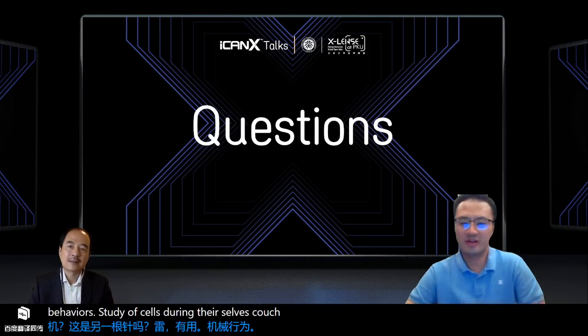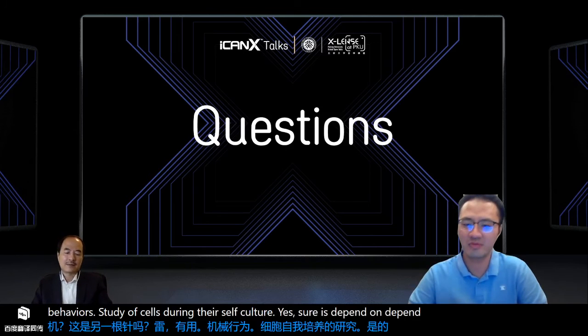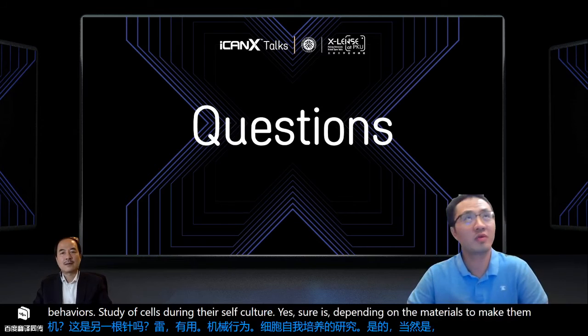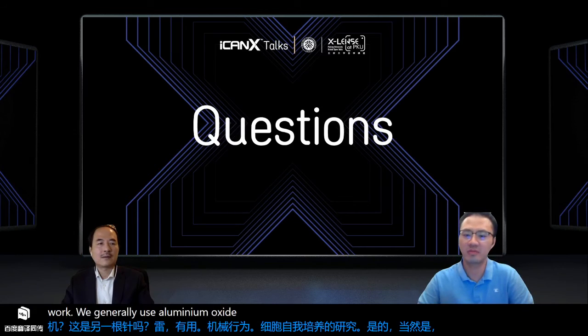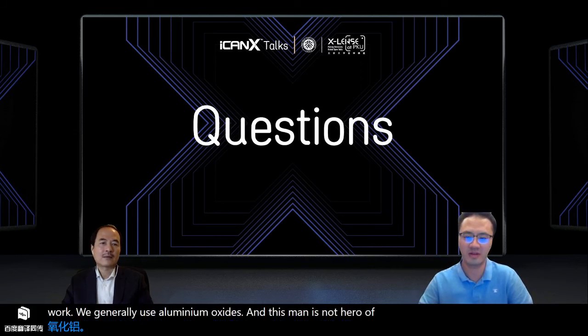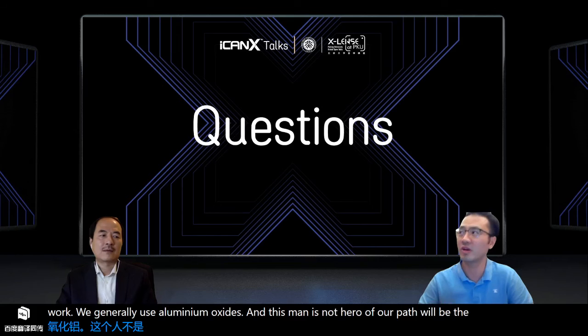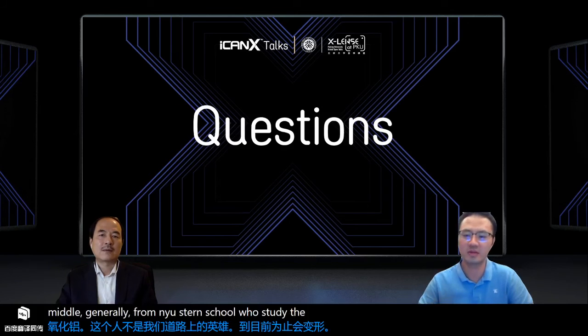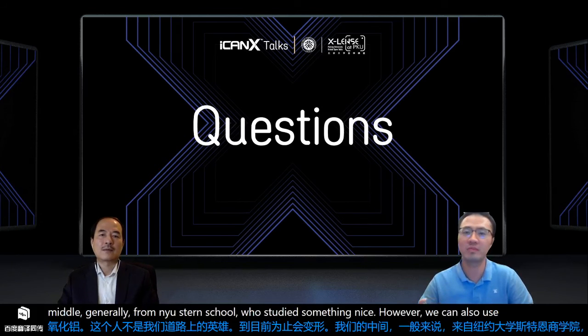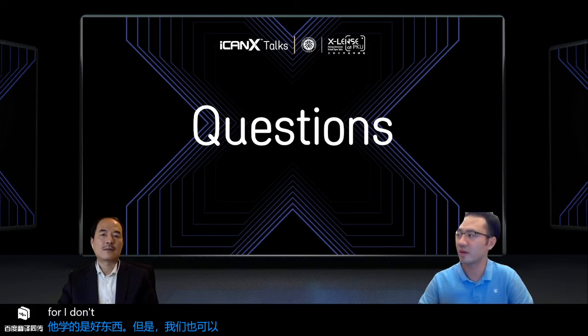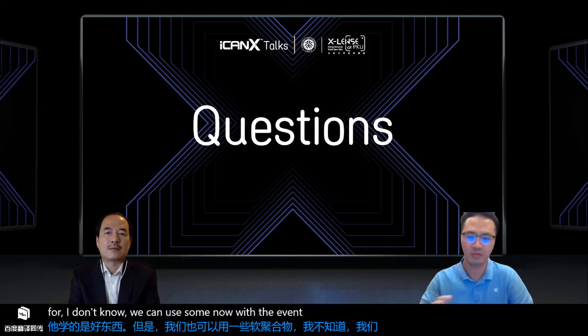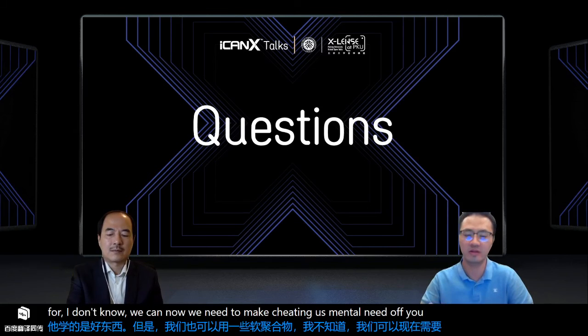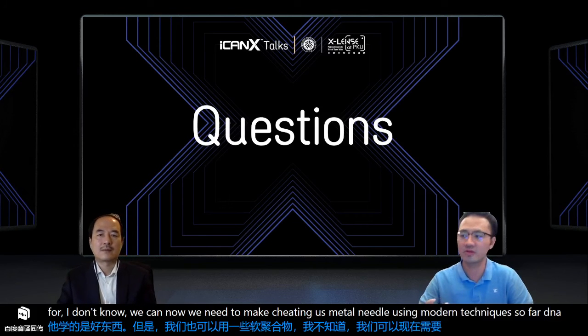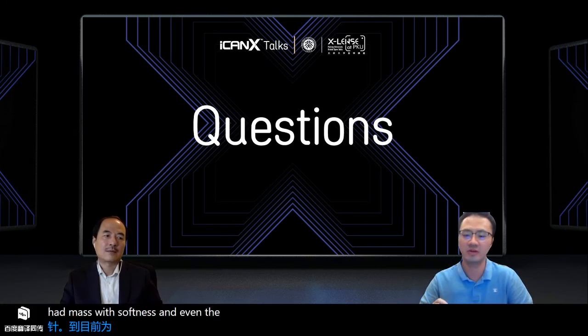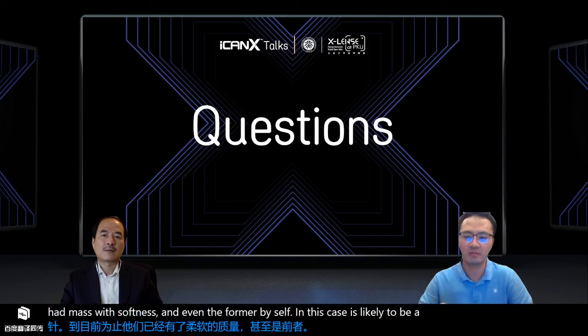Oh, yeah, sure. It depends on the material that we use to make the nanoneedle. For our work, we generally use aluminum oxide or metal material to make the nanoneedle. And this material is tough and hard to deform. So we generally don't use them to study cell mechanics. However, we can also use some soft polymer to prepare the nanoneedle. For example, we have already developed a technique to make PDMS nanoneedles using molding techniques. PDMS has much greater softness and can even be deformed by cells. In this case, it is likely to be applied for cell mechanics study.